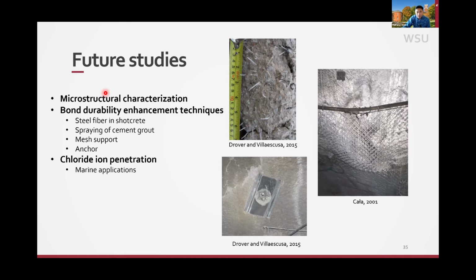And of course, more studies need to be done. One is to look at the microstructure, look at the bond, why there's a failure, what kind of failure, adhesive, cohesive, all those things we need to look at more closely. And also look into other methods so we can increase the bond durability, especially in cold areas that have a lot of freeze-thaw cycles. For example, adding steel fiber in the shotcrete has been reported to increase the durability of the bond. Or before you apply the shotcrete, you can apply a layer of cement grout, hopefully increasing the bond between the shotcrete and concrete. Or you can use a physical method using mesh or anchors.